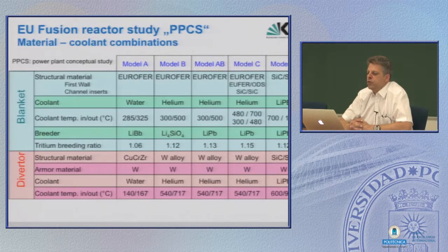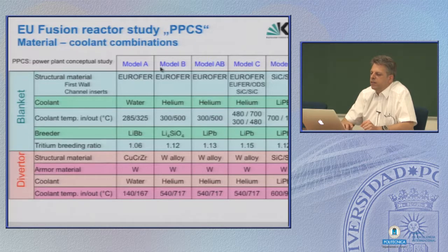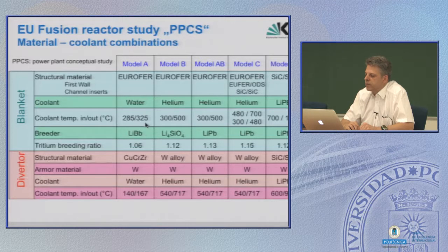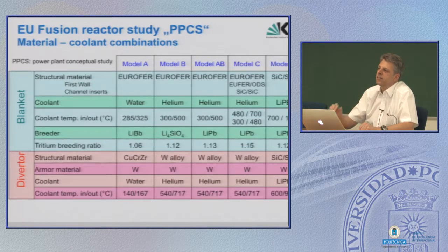Now, the European fusion community has performed a so-called power plant conceptual study, PPCS, that's several years old. They have come up with 5 different models. We don't have to go into the details here. In principle, the main differences are in the blanket in terms of coolant. There is a water-cooled concept, and this would operate at temperature ranges comparable to pressurized water fission reactors, meaning inlet temperatures of 280-285 degrees C and outlet temperature 300-325 C. If you remember also yesterday, exactly this range around 300 C was the temperature range where the 9% chromium steels faced the highest hardening and embrittlement.